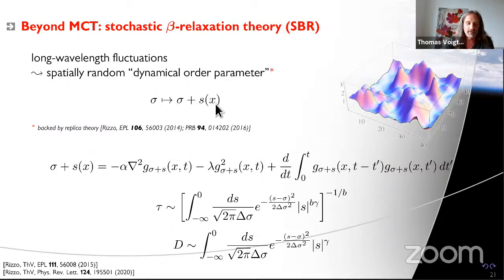So it has a mean sigma, and there should be zero-centered Gaussian fluctuations around it. So the picture is a little bit like I tried to sketch here. Never mind the axis, but if you imagine, for example, the density in the system to have spatial fluctuations on long wavelengths, and there will be some regions that happen to be dense enough to be glassy, and some regions happen to be not dense enough to be still liquid-like. And you can express this in terms of a fluctuating distance to the glass transition point.